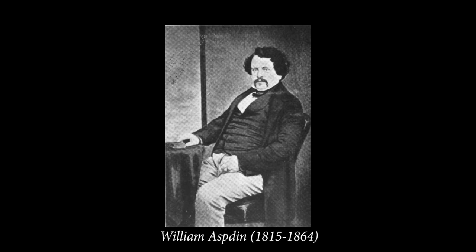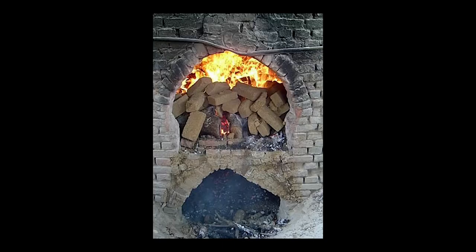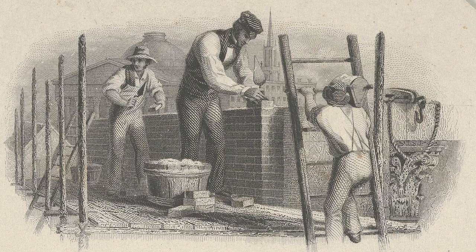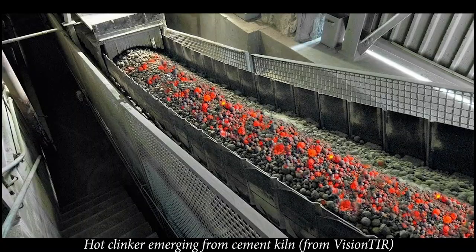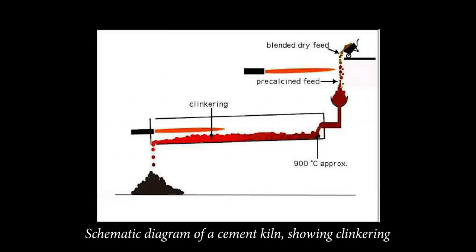But it was much weaker than the Portland cement of today until the 1840s, when Aspdin's son William accidentally made the key advance. A batch of cement had been left too long and too hot in one of the kilns and had seemingly burned. It was hurriedly mixed up and used anyway, and the result proved much stronger and more durable than usual. Repeated experiments showed this was no anomaly, and the process of clinkering, burning the lime and clay until they melted and reacted to form hard, strong calcium silicates, became standard in the Aspdin family cement business. The powdered cement was then made by grinding up the clinker.